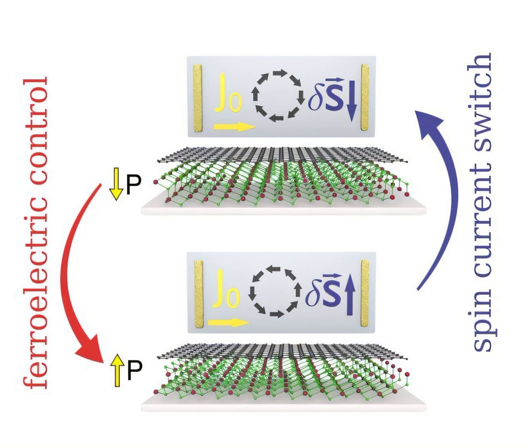The new research introduces a graphene/In2Se3 heterostructure platform where the ferroelectric polarization of In2Se3 modulates the spin-orbit coupling in graphene. Simulations show that flipping the polarization reverses the sign of the Rashba-Edelstein effect, switching the chirality of spin textures and the spin current direction, all without magnetic fields and with minimal power consumption once the polarization is set.